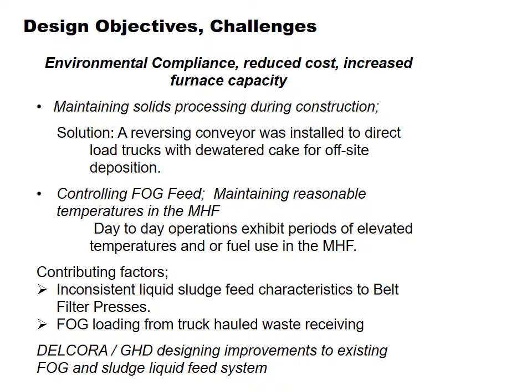So some of the challenges we ran into were maintaining the process because they're taking these trucks every day and the stuff's coming down. So before we did the construction, we put a conveyor out the window from the dewatering. They use belt presses, and they get about 25 to 30% solids on the belt presses because they have a paper mill that gives them a lot of fiber. Worked with Material Matters in identifying an outlet for this material during construction. Did a very nice job for us to identify a place where we can take unstabilized sludge.